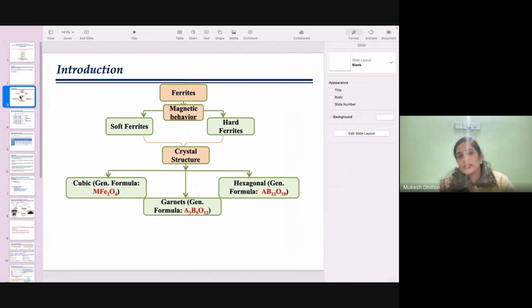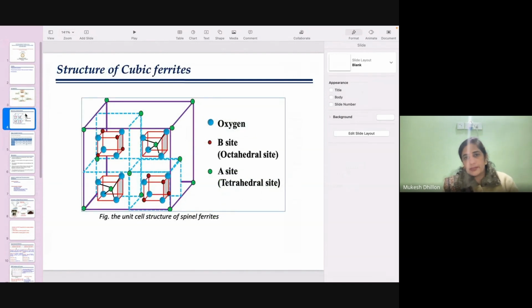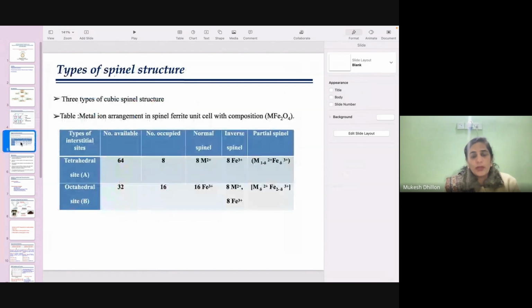Ferrites are divided in two types on the basis of magnetic behavior, soft ferrites and hard ferrites. On the basis of their crystal structure, they are divided in three types. Cubic ferrite having general formula MFe2O4. Garnets having general formula A3B5O12. Here A, B, M are metal ions. The third one is hexagonal, BaFe12O19. I work on the cubic ferrites and their structure is spinel, that's why they are also called spinel ferrites. In their crystal structure, there are 32 oxygen ions, which create octahedral sites and tetrahedral sites. Octahedral site is also called B site and tetrahedral site is called A site. On the basis of the presence of the metal ion on these A and B sites, the cubic ferrites are further divided in normal spinel, inverse spinel, and partial spinel.